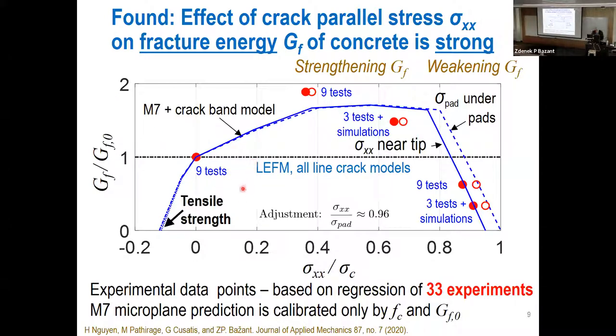According to all line crack models, LEFM, the cohesive crack model, XFEM, there is no effect of crack-parallel stress because the crack is considered a line, with no fracture process zone width. So that grossly disagrees with test data. For concrete, the data indicate almost doubling. These are the points. Now I show two of them. One is for the stress measured on the pads, and it's slightly different at the tip of the crack, where it's a uniform view, also shifted. And so it goes up and then goes down and eventually goes to zero when we approach compressive strength.